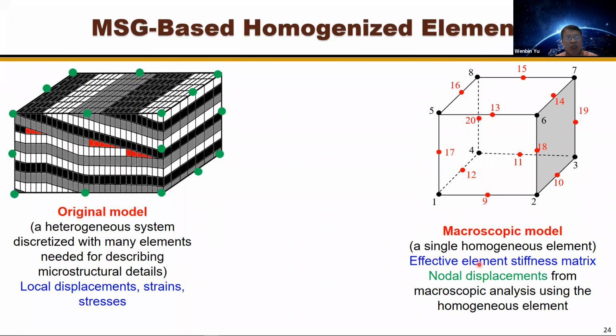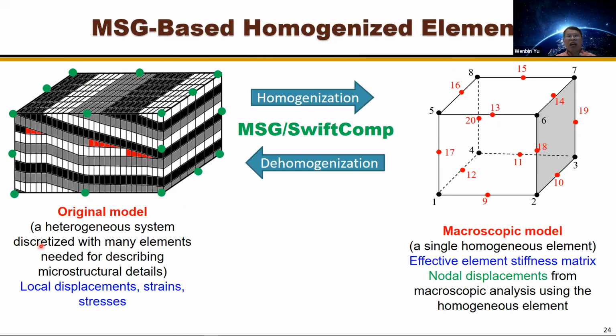I want the effective stiffness matrix so that I can do the simulation to do the global analysis, but this will help us to get local stress and strains. Then I can do homogenization to get the effective properties. For this purpose, it is the effective element stiffness matrix. It's not the material stiffness matrix anymore. For example, a 20 node element, you're talking about a 60 by 60 stiffness matrix. And after you've done the global analysis, you do a dehomogenization, and you get all the local stress within the original material. You apply your failure criterion, whatever local buckling criterion, at that level.